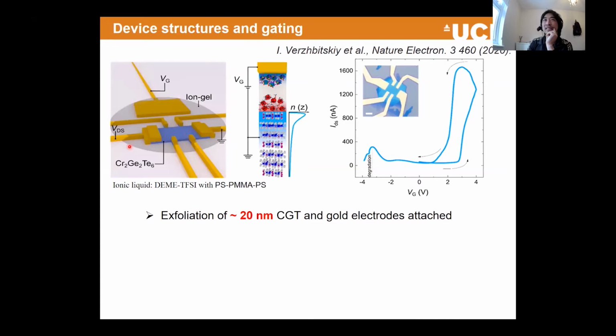So this is a schematic of our device. We have this CGT, we put the contact next to it, and then we put the ionic gel. This is a nice electrolyte so that we can apply a large amount of charge accumulation through the interface. That's fairly typical for the 2D materials community. Now this is like a FET structure. When we apply a voltage of a few volts, plus and minus, at 0 volt we don't have any significant source-drain current. But once you increase the voltage to close to 4 volts, you can see a really nice current going through the channel. So this is the turning on of the FET structure, shall we say.